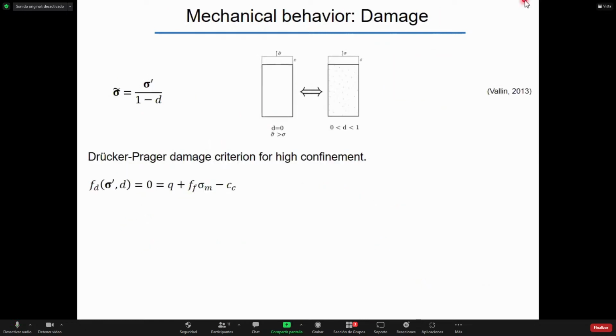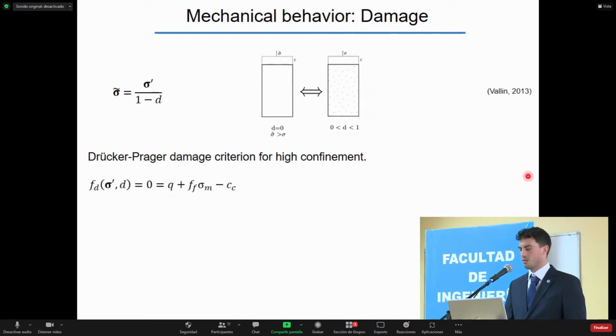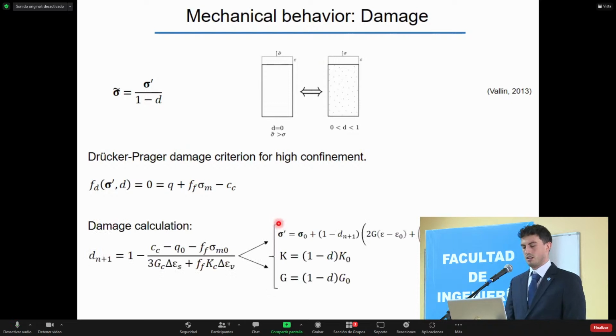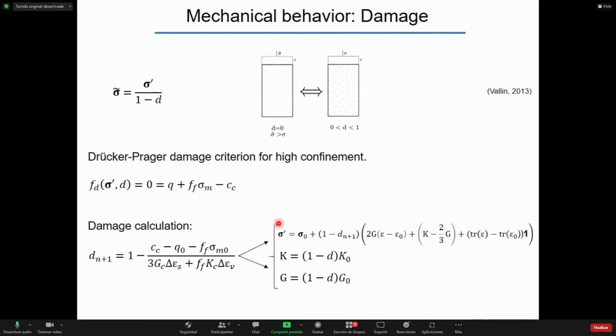In addition to the carbonation damage, the program also considers an isotropic damage, which simplifies the equation to a single variable d, and it uses a Drucker-Prager damage criterion for high confinement. The calculation of the damage depends on the Drucker-Prager criterion, the stiffness, and the imposed deformation. And from here we can determine the new stress state as well as the new damage moduli.